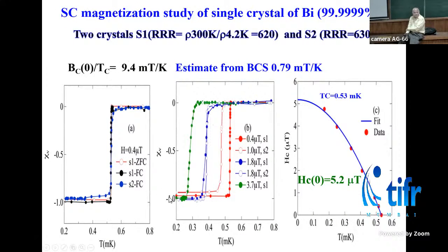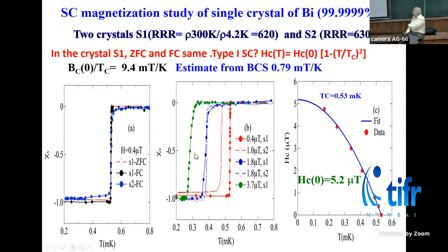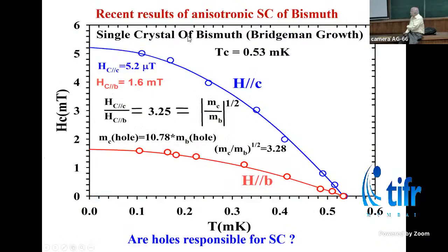Then we did the superconductivity of bismuth, where we showed that it really does superconduct, with a 5 microtesla field. Many things are missed by our experts: the Earth's magnetic field is 50 microtesla. If you do the experiment without shielding the Earth's field, you will never see superconductivity at any temperature. So we need to shield it below nanoteslas. There is a way to do that, and we did that, and that's how we got the superconductivity, and we see it's a type 1 superconductor and so on.